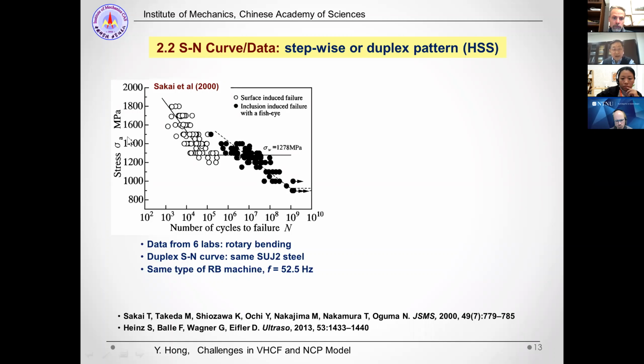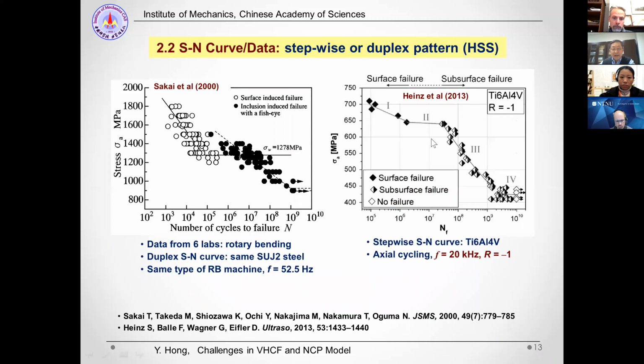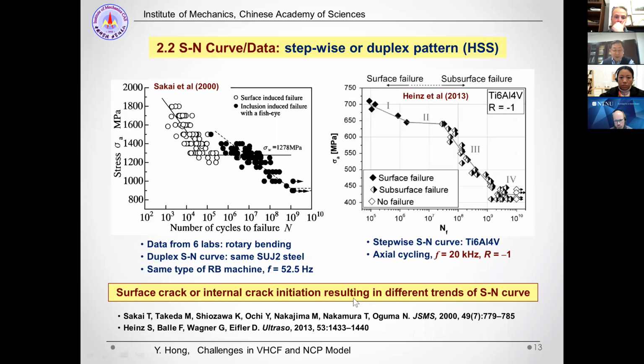And we can see it's what is called the duplex SN curve or stepwise SN curve. That is for this high strength steel, but for titanium alloy there is also a stepwise SN curve trend, and it is also due to surface crack initiation and subsurface or internal crack initiation. So due to the different types of crack initiation, from the surface or from the interior, they will result in different trends of the SN curve. That's the second point.